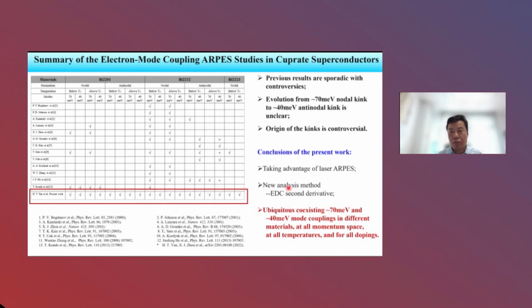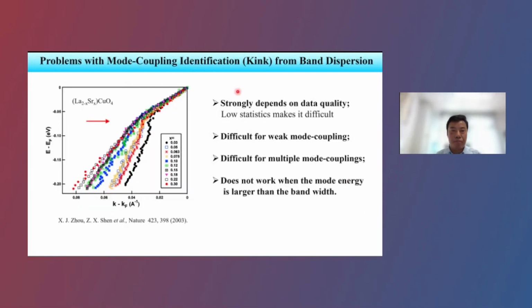So basically, this is the conclusion of this topic, and later on, I'll give you some data to illustrate this conclusion. Previously, people used the kink in dispersion to identify this electron-boson coupling. This method has some shortcomings. Mainly, it depends on the data quality, on the statistics. When the data statistics is not good, or when the mode coupling becomes weaker, it's hard to make a conclusion. Also, when there is more than one mode coupling, it's also very hard to identify.